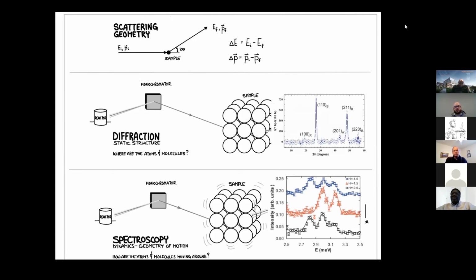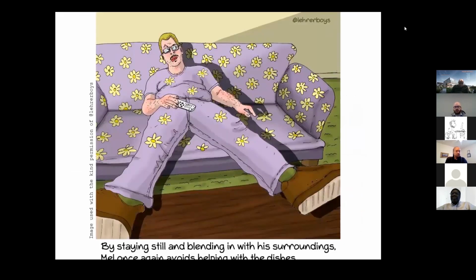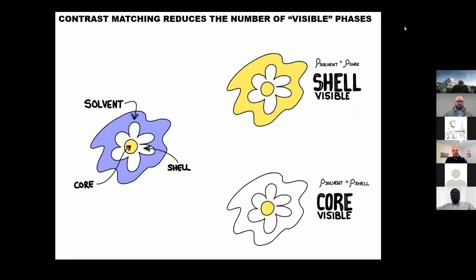So I mentioned earlier about the fact that deuterium and hydrogen have very different contrasts. So this cartoon shows what I mean by contrast matching. So this character, Mel, has basically contrast matched his outfit to the upholstery on the couch, okay? And what you can make out is his head, his arms, and his feet. And this is actually sort of what we do in neutron scattering to simplify our measurements. We often measure samples that have multiple components to them. And so on the left-hand side here, I'm assuming that my multi-component system is composed of a core in the yellow, a shell in the white, and then the solvent is the violet.